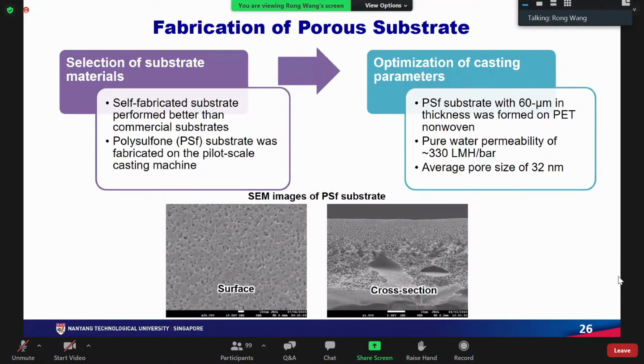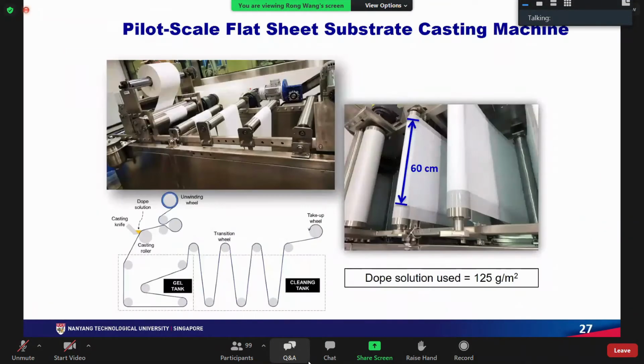The first step for us in this project is to optimize the substrate. We developed a new substrate by ourselves using polysulfone material. We fabricate polysulfone UF type membranes on pilot scale casting machines. The optimized substrate has water permeability around 330 LMH per bar with average pore size around 32 nanometer. Here are the photos of our pilot scale flat sheet casting machine. I also prepared a short video to give you a rough idea how this machine works.